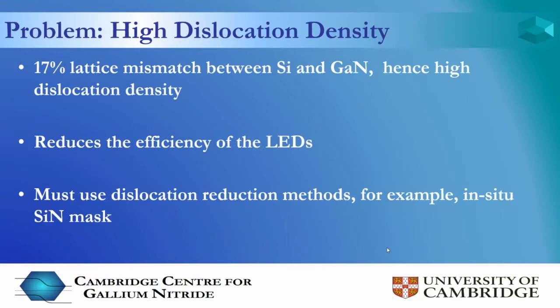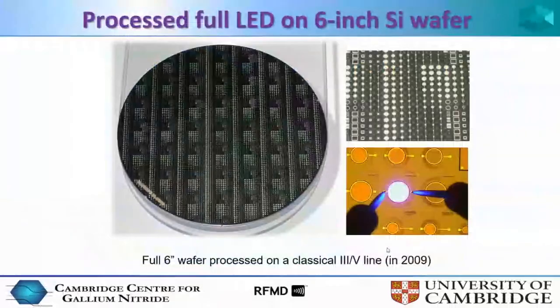So we solved all these problems, and this student managed to get LED structures, not very efficient to start with, but he demonstrated it could be done. And then after further work, in 2009, this was a 6-inch wafer of gallium nitride on silicon, and these patterns are LEDs. It's a test structure, so it's LEDs of different sizes, and that's the blow-up on the top right, and this is just an individual LED, passing electric current through these two electrodes, which are just two contacts. And this is emitting blue light, which is so bright it's saturated the detector, so it looks like white light. And this was the first gallium nitride LED system on 6-inch silicon in the world, which we did in 2009. And we used industrial fabrication silicon to process it.